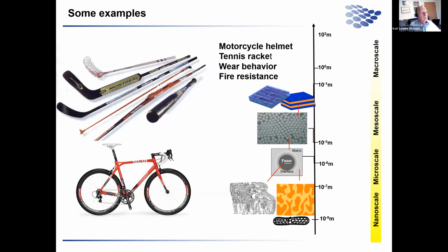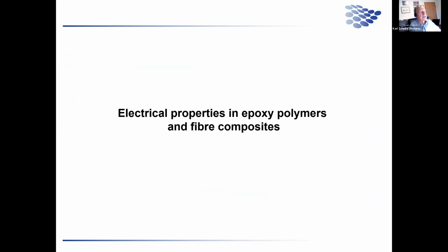It's mainly important for hobby cyclists, who have quite a lot of accidents in this case. So if you have a bicycle with a carbon frame, be very careful and don't let it fall down against a stone or something like that. But you see, fracture toughness is very important. The other thing is with motorcycle helmets, where it's very important to have later damage tolerance, higher fracture toughness, maybe also fire resistance and other things.